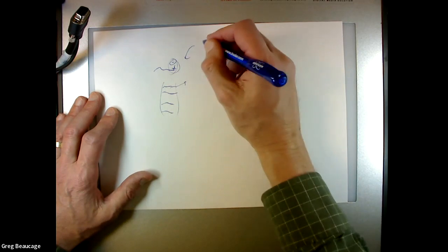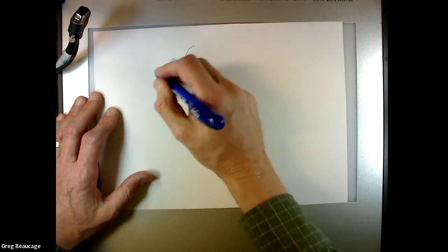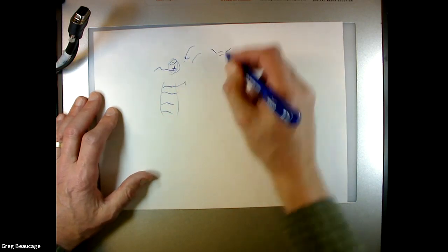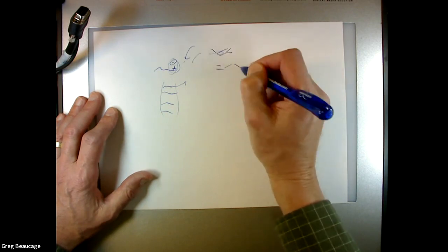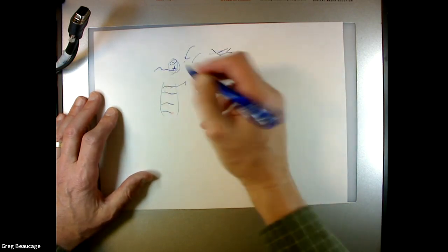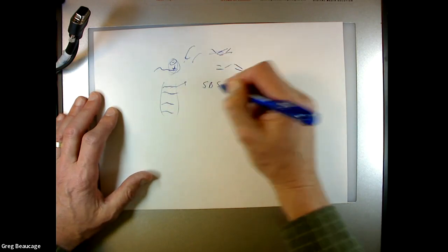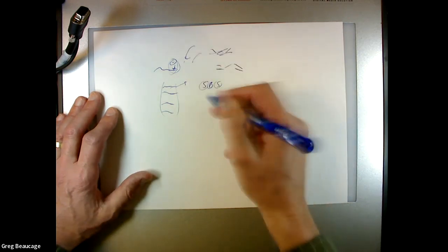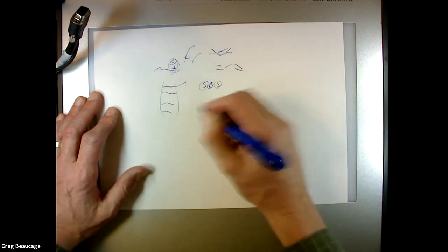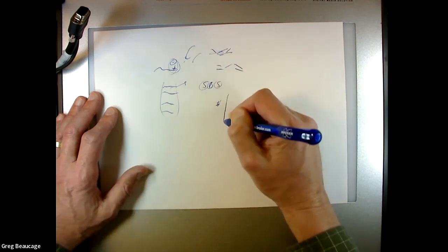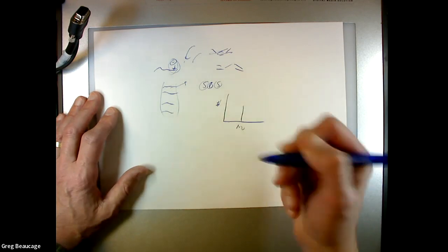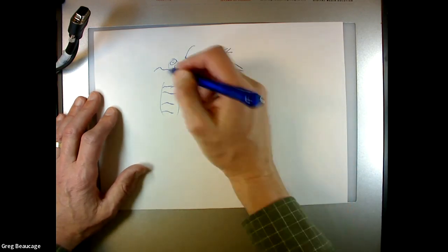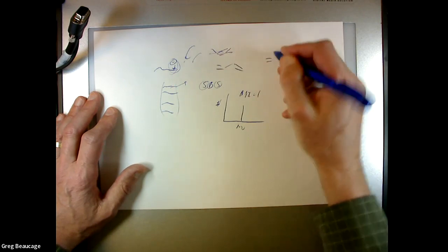Also with anionic, you can grow it until all your styrene is eaten up, and then you can put in butadiene, this monomer, and grow that one. So basically, you can make styrene, butadiene, styrene block polymers with fixed monodispersed molecular weights. If you plot number versus molecular weight, you'll get one number basically. PDI is 1.